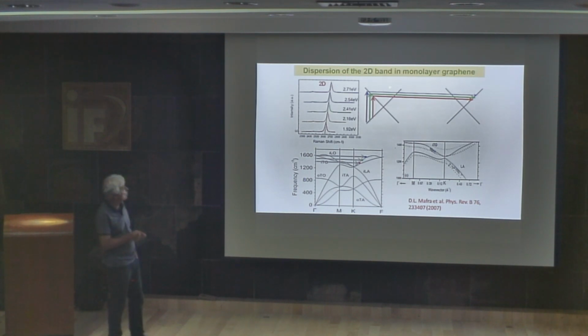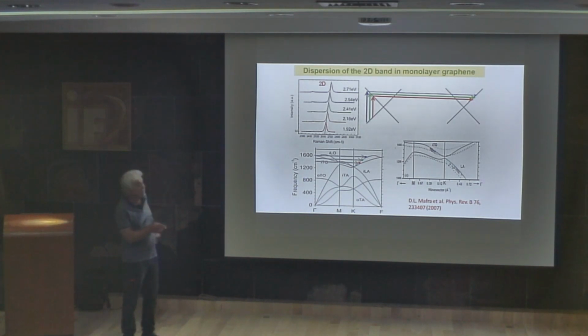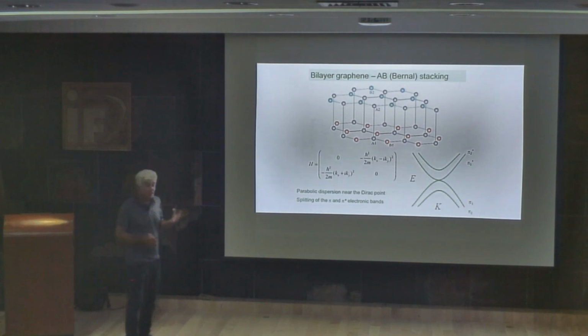This is just to show that if I put those arrows here in the phonon dispersion, I'm probing the phonon dispersion of what we call the transverse optic phonon. And that's why I see this kind of dispersion. So the idea is that using this 2D band, we can probe phonons in the interior of the Brillouin zone of graphene. Okay, but now what happens if we have 2 layers of graphene?